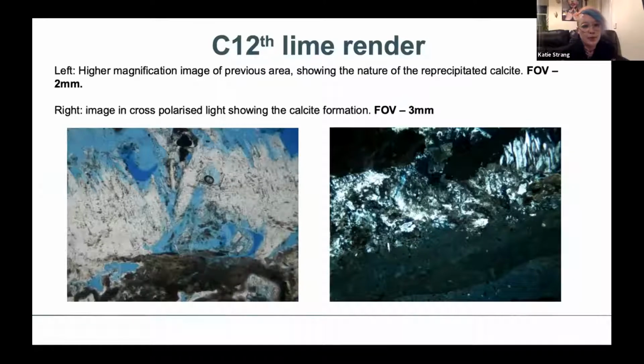And this is another image to show you. The left is in plane polarized light, and the right hand side is in cross polarized, and you can see how dense that is there, and there's not a lot of blue space in this region. So that again tells us this is likely one of the factors that we're experiencing these problems. But it is important to say that if you're looking at a material that has failed, there can be a whole number of reasons, and it's really important to work with the people that are working on the building. So that's the contractors, the architects, anybody that's involved with the project. It's good to try and get an idea of what's going on, because there are so many different factors that can contribute to this.